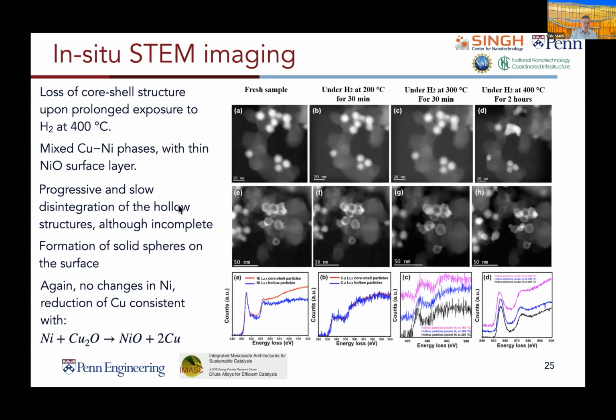So if we go back now and image, we find that the core shell structures are removed during high exposures in hydrogen, and you end up instead having a copper-nickel mixed phase that often has a thin nickel oxide surface layer. So again, that's consistent with this equation down below. With time, there's a progressive and slow disintegration of the hollow structures. They don't completely disintegrate, but they begin to collapse upon each other and form solid spheres, again, with a nickel oxide on the outer surface.